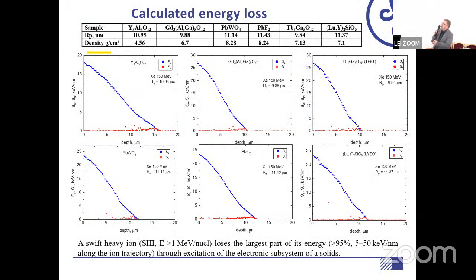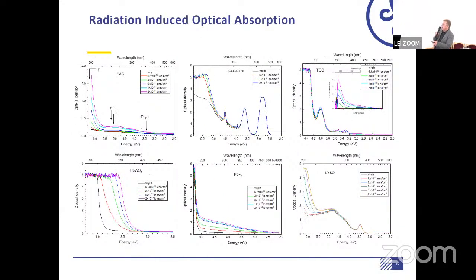Our last test of a few important materials for CERN applications was done using irradiation again in Kazakhstan. You can see here data for small radiation doses, and then we discovered some important changes in the optical absorption of this crystal. What was most interesting is that before this experiment there was no data concerning the absorption edge at about 6 eV, which is still important for detector application. And now we are analyzing this part by thermal annealing.